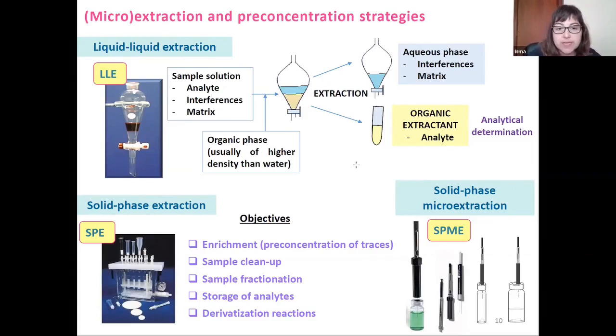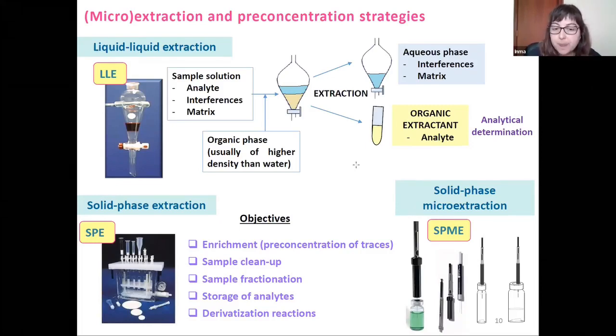Solid phase extraction is based on the retention of the analyte from an aqueous solution into a sorbent or a solid phase. Mainly, there are two objectives in solid phase extraction that are analyte enrichment and sample cleanup. Another technique that derives from the solid phase extraction is solid phase microextraction, SPME, where a fiber of fused silica is covered with a polymeric stationary phase and allows the extraction of different analytes. Usually, in both techniques, the analyte elution from the sorbent is required before analysis. In the case of solid phase microextraction, this desorption is performed by the addition of organic solvents or by thermal desorption, since typically the analysis is performed by gas chromatography and HPLC.